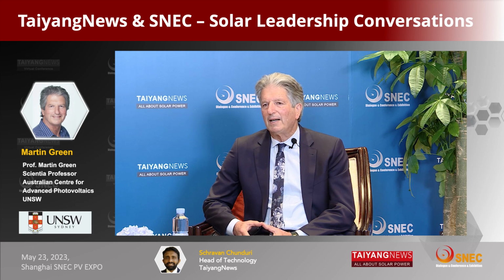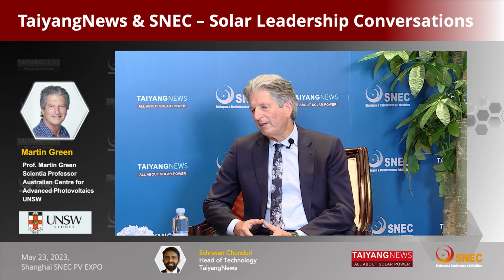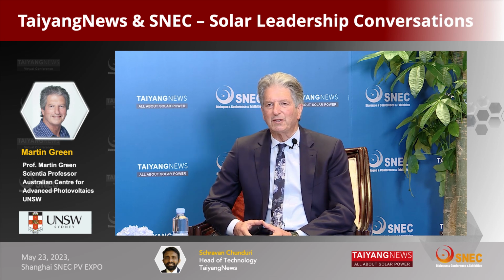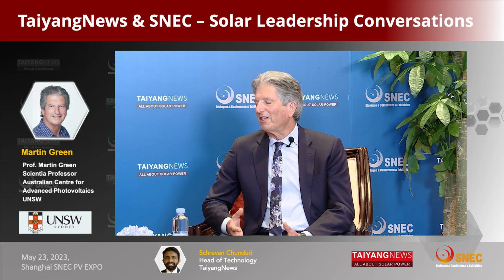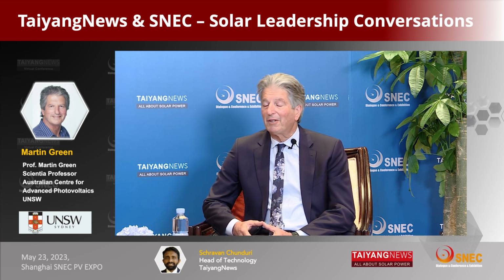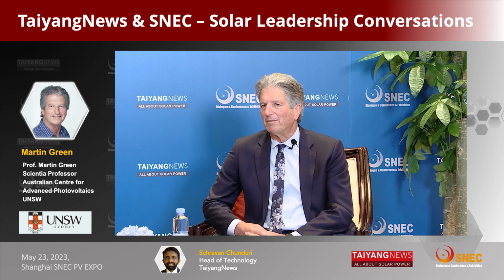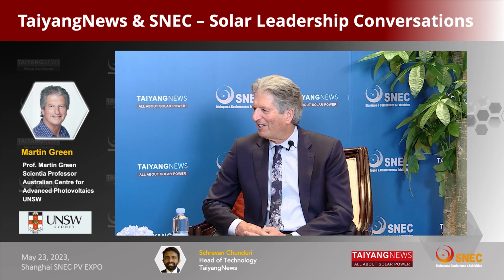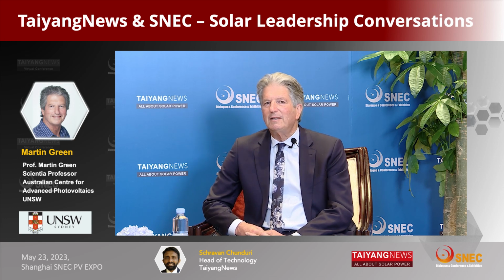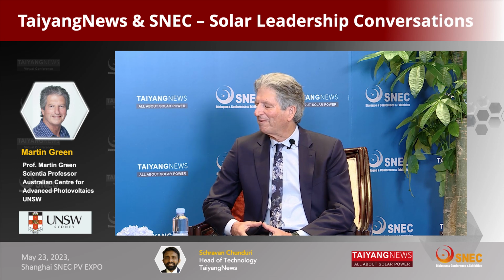And there's little evidence that that situation's been obtained. Then there's all the issues with reverse bias of modules, which even silicon has challenges with. So the perovskites are going to be more prone to reverse bias effects than silicon modules. I don't think that type of issue has been seriously addressed by those working on perovskite cells at the moment. But if you're going to field them in 1500 volt systems, they're going to encounter some quite severe reverse bias issues that are going to need to be resolved before you can really have a commercial product, I think.